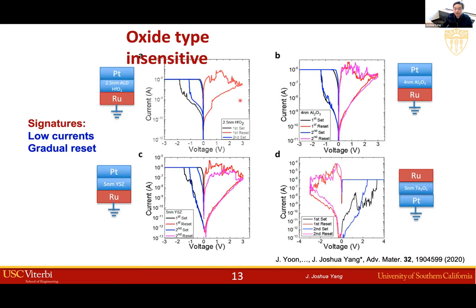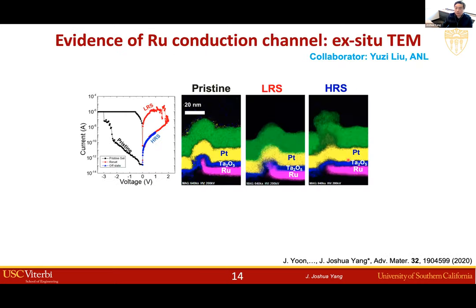In this demo, in fact, we made devices with different oxide layers, but all the devices have a ruthenium electrode. As you can see, as long as you have a ruthenium electrode, regardless of the oxide, you get similar switching behavior, all gradual switching and low current. So this is related to ruthenium. And then we want to know how and what's going on.